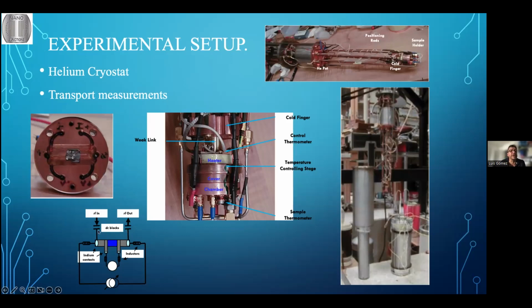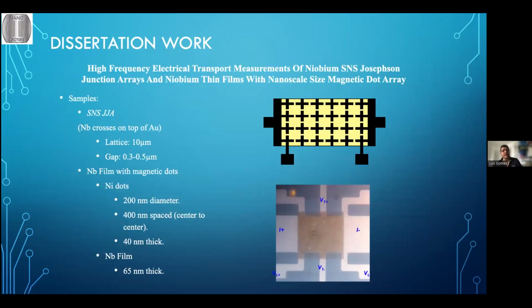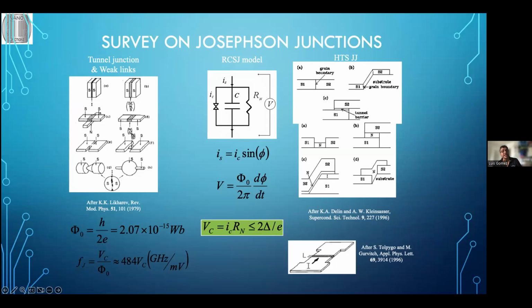And then this is a little representation of how the samples are measured. On the samples, we can also apply microwaves. So we have these mini coaxial cables going into the sample, and then besides a DC current, we can have an AC component. This AC component basically will add up to the DC voltage, and then we can do experiments based on frequency, and change the characteristics, and I will show that later. So it is important to be able to add this AC signal to the system.